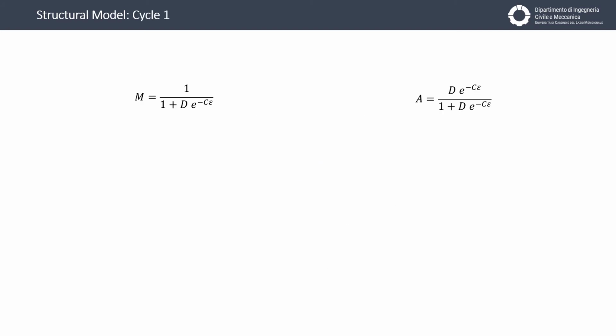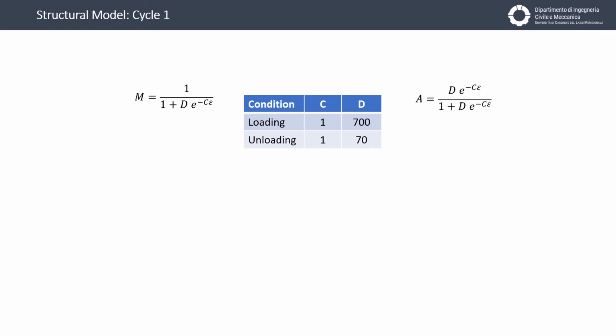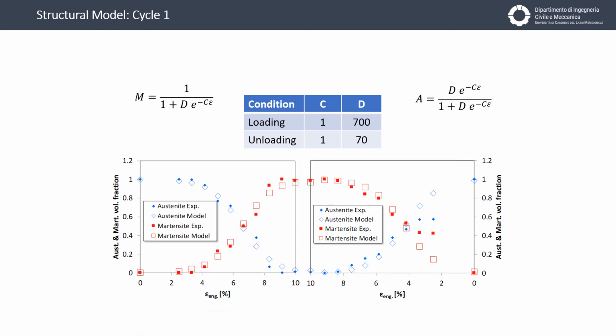Considering the results in terms of quantity of martensite and austenite taken from the step-by-step tests in loading and unloading condition at the first cycle, we can calculate the values of the parameters C and D. You can see that C is always equal to 1 and D changes from 700 to 70, and in this case the parameter D takes into account the hysteresis of the material. In the graph you can see how the plotted functions seem to fit well the quantity of measured microstructures.